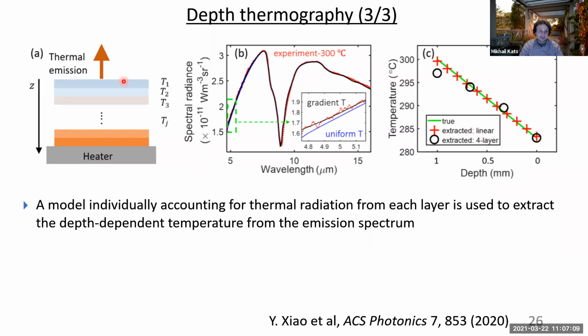And the way that this calculation is done over here is using just a thin film formula, a transfer matrix formalism including the fluctuation dissipation theorem to figure out what the total thermal emission is going to be if you have different temperature sources at different positions throughout this thin film stack. And so then once you do this inversion, and this is something that's quite difficult to do because this is a pretty poorly conditioned problem, you have to have very precise and accurate measurements of your thermal emission spectrum, which fortunately we do. But once you do this inversion, it actually works pretty well.